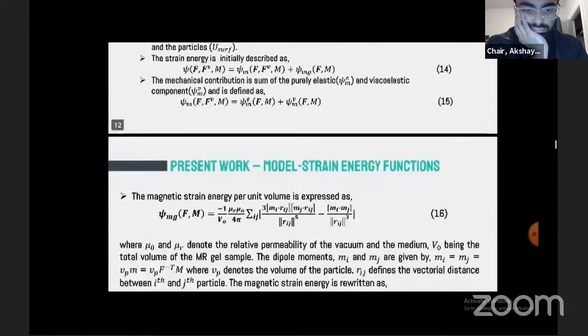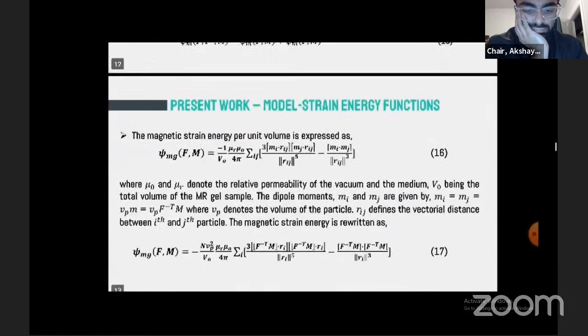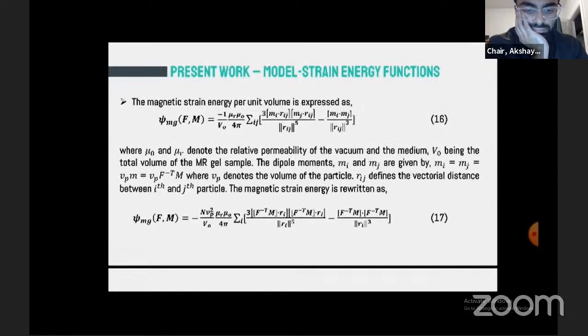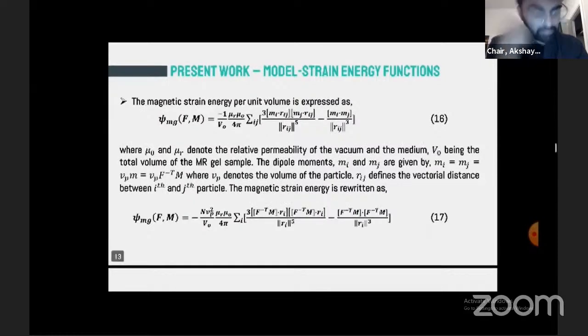So for the magnetic strain energy, the strain energy functions, we'll start off deriving. The magnetic strain energy per unit volume is described as shown in equation 16, where mu naught and mu r are the permeability of the vacuum and the relative permeability of the medium respectively, with V naught being the total volume of the MR gel sample. The Mi and Mj terms are the dipole moments, and small vp denotes the volume of the particle. Here, rij denotes the vectorial distance in the spatial configuration between the ith and the jth particle. Using this information, equation 16 is rewritten as equation 17.